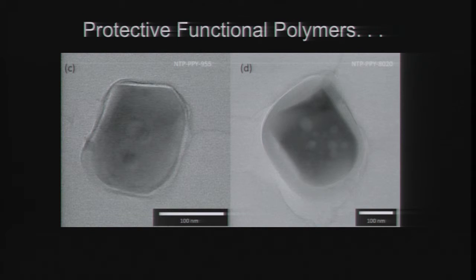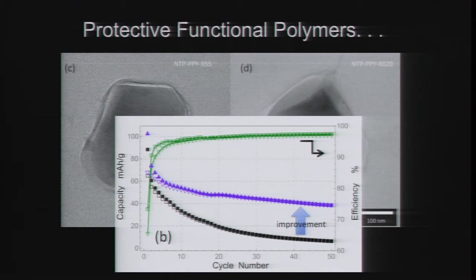And these are two different thicknesses. In this case, it's quite thick. In this case, it's very thin. Turns out there's a Goldilocks thing where if you're too thick, you don't get very good performance. If you're too thin, you will actually not protect the material. But if you get it just right, you can dramatically improve the long-term performance of this material.